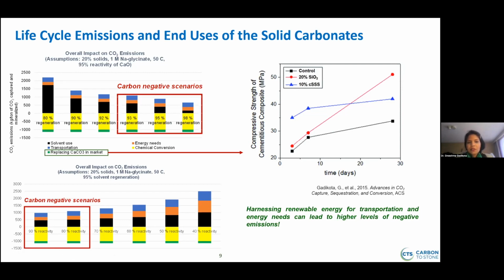So to achieve net carbon negative for a situation where we have about 20% of the solids loaded, we need to have at least 93% of the solvent that is regenerated or recovered per cycle. Similarly, if we're looking at alkaline residues, we need to achieve reactivities that are more than 80% or higher in order to achieve net carbon negative scenarios. Again, this is assuming that we're transporting the solids, assuming that we're using fossil fuels for transportation, and such.